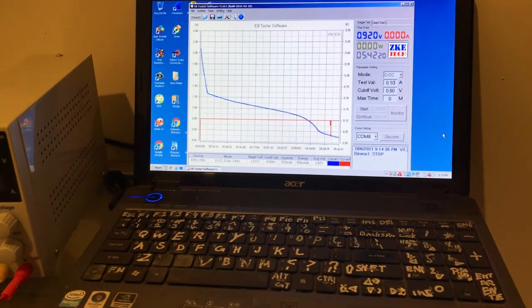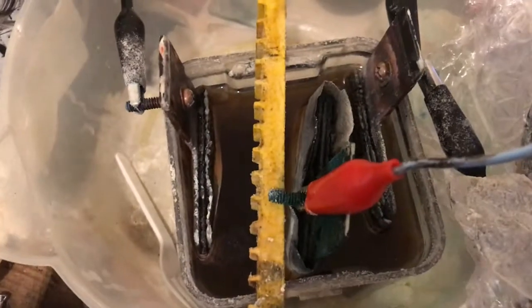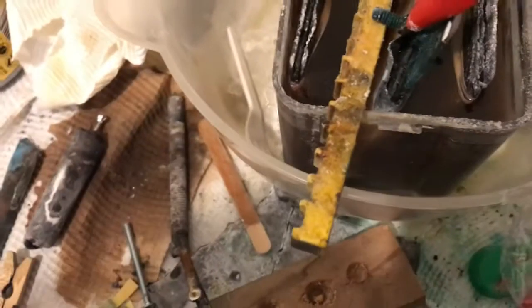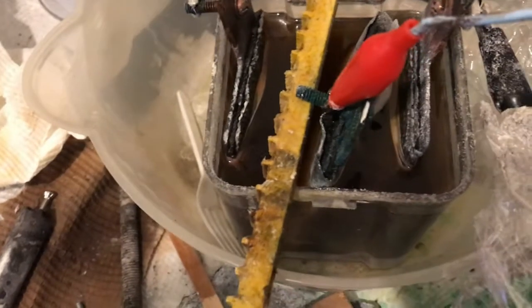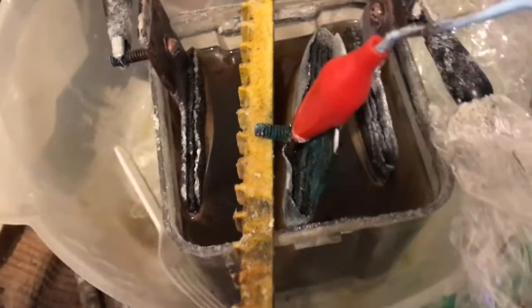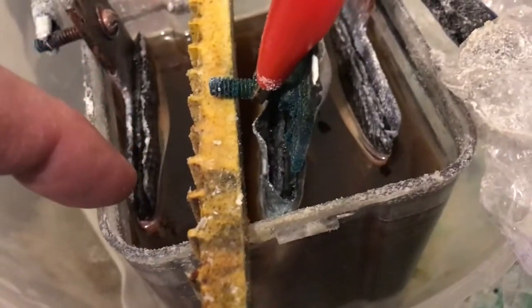Alright, the 50th run is complete. 5 hours and 42 minutes. 570 milliamp hours and 555 milliwatt hours. I didn't think the cell had any extra in it, but it seems to be still increasing. Or on this run it did anyway. Maybe because I topped it up with some extra water and increased the surface area by raising that liquid to the top of the plate. It could probably go a little bit higher, the liquid that is. If we go to the top of these things, there'll probably be a little bit more in there.